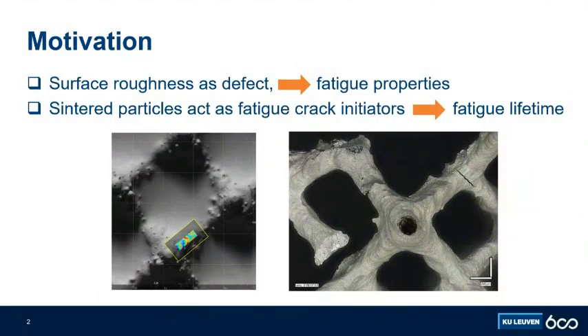The motivation behind the work is that surface roughness can be considered a defect, further deteriorating fatigue properties. And sinter particles inherent to the laser powder bed fusion manufacturing process can act as fatigue crack initiators, directly reducing fatigue lifetime. And because lattice structures display a high surface to volume ratio, this effect is even more pronounced.